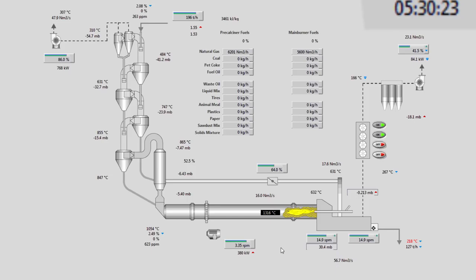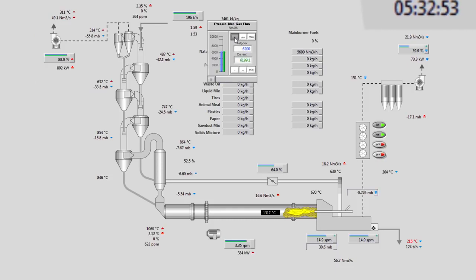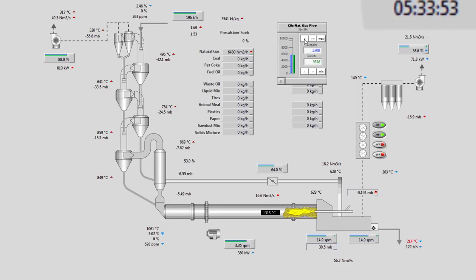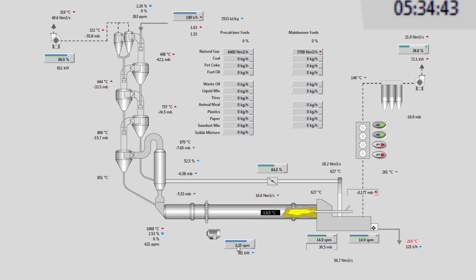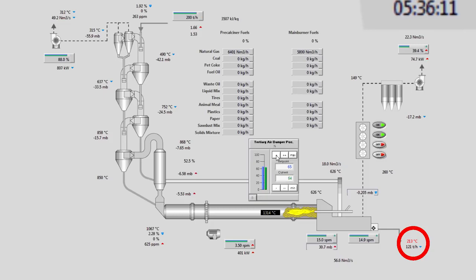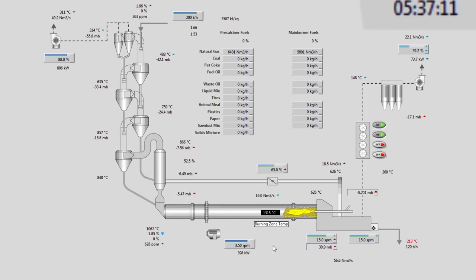Five hours 30, getting ready to add the last 4 tons. Preparing the system with additional draft. A bit more fuel. The feed. And the speed. I see that my clinker temperature is extremely high. Time to work on the cooler and improve the overall system to achieve a better heat consumption and assure clinker quality.